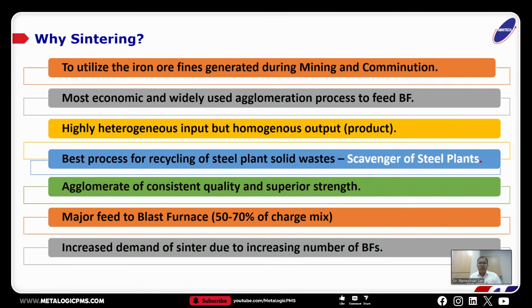So this almost two-thirds of the material produced in mining, how best can we utilize it? For that, agglomeration is required. Sintering is probably the most economic and widely used agglomeration process. The input is a heterogeneous mass, but once you make the product, it is highly homogeneous and very consistent, with embedded properties that are very good, such as porosity and strength, which make it the main feed in the blast furnace. It is basically the lifeline of the charging material for the blast furnaces.